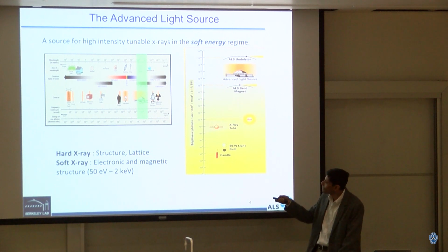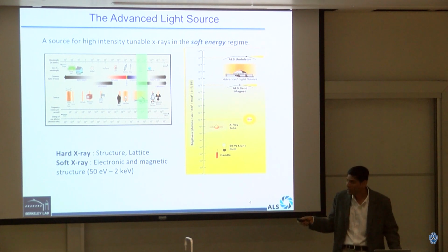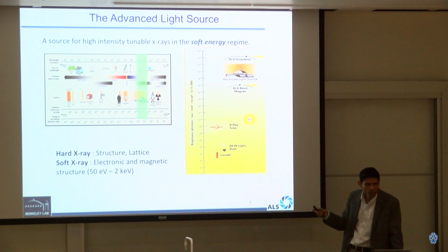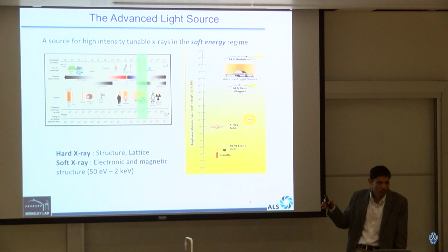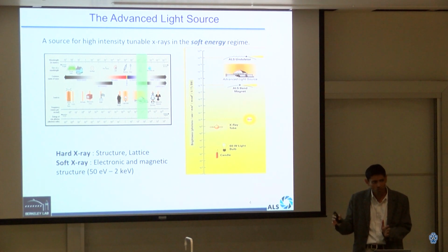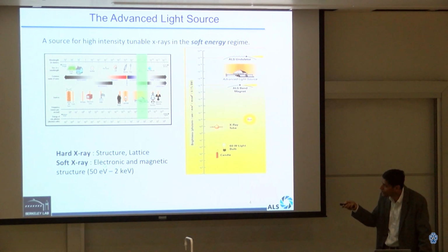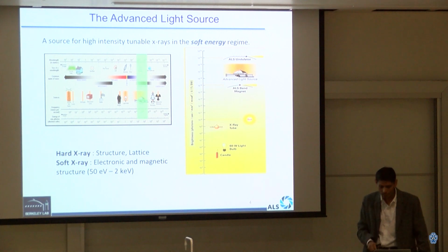I will show later on, I have a slide. But this way, if we just go simply with Bragg's law, 2d sine theta equals lambda, then the d-spacing that we can probe is say 5-6 angstrom, possible with a hard X-ray. But for soft X-rays, the wavelength is something like 15-20 angstrom. So in that case, we can't probe the lattice anymore. But it just turns out that the magnetic features, a lot of the time, the domains and skyrmions and other magnetic features or electronic features like ferroelectric domains, are 100 to 200 nanometers. And then this 2 nanometer wavelength beam from soft X-ray becomes very, very important. And then you can also do a similar Bragg law analysis to study those features. And then I will tell you a little bit about how we get this electronic and magnetic sensitivity, and you will see that. I think that's a very good question.